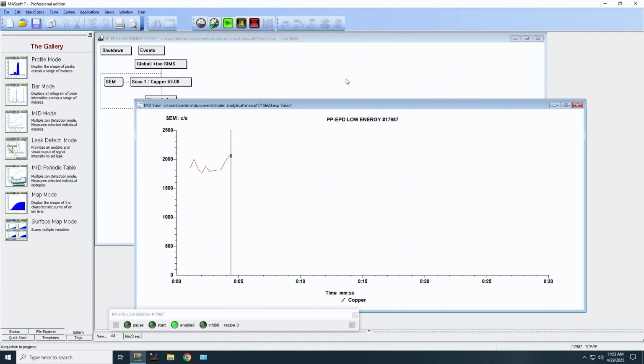All right, so there's the data. There's no copper being etched right now, and we're seeing a signal of 1800 counts, so that can be considered the background level. The background level will go up and down as the vacuum in the chamber goes up and down. If you want the highest resolution, you actually have to wait about half an hour after transfer before etching, but we don't need that today, so I'm just going to get started.